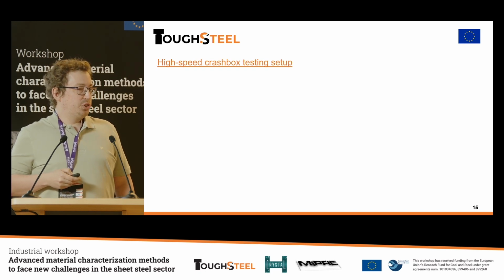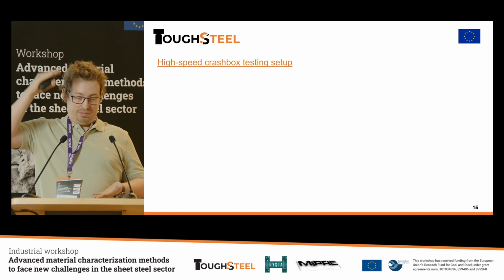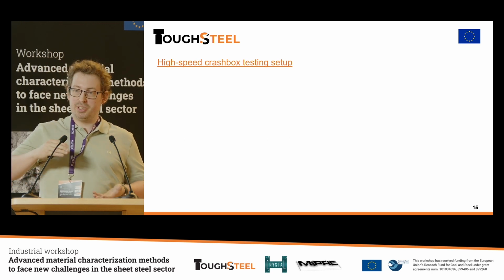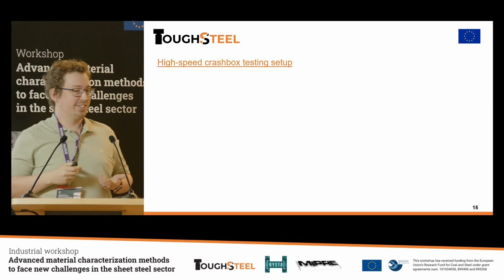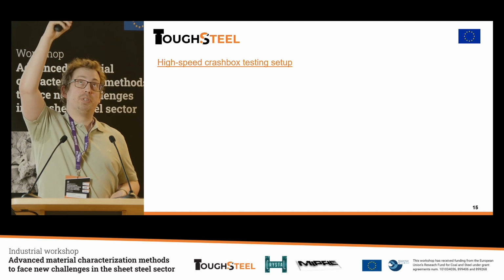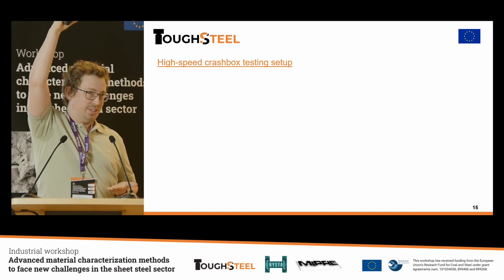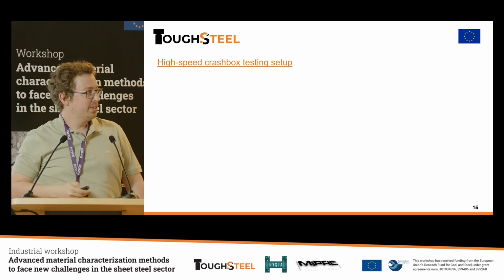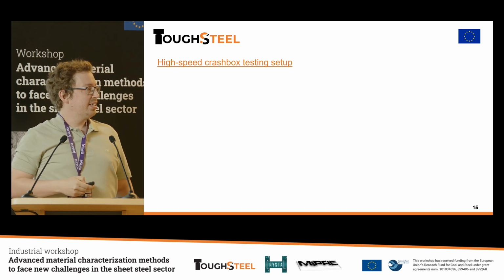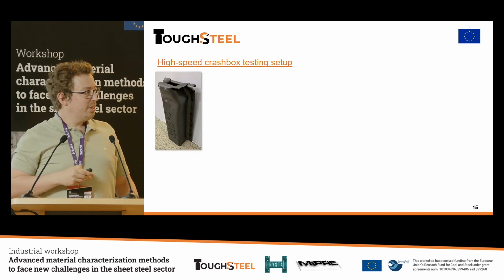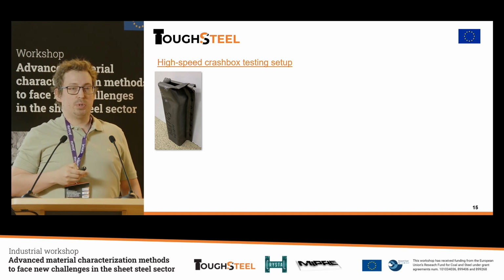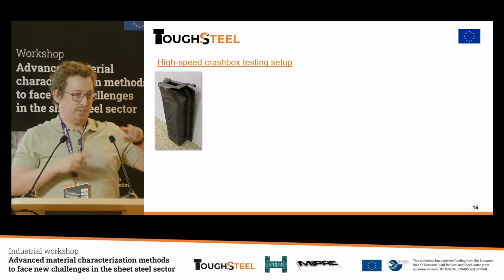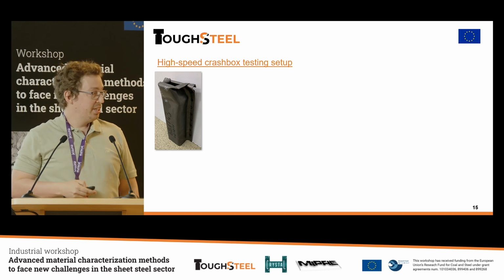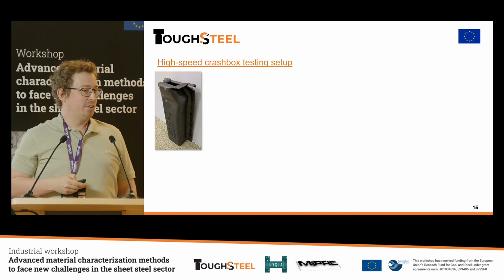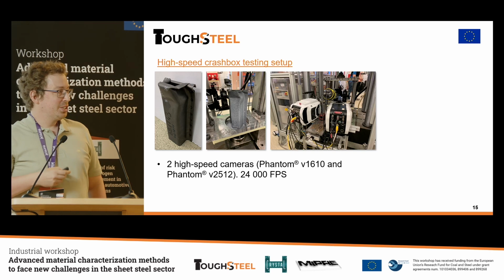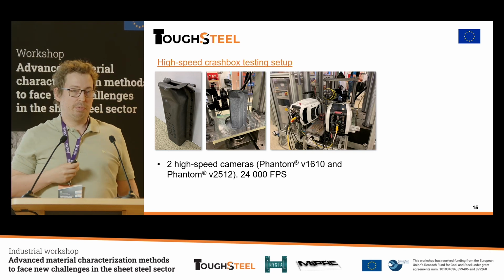And usually you use fall towers, like drop towers, to perform this with a huge weight. You drop it from a high level and crush the boxes like that. We don't have that. And usually you have maybe 5 to 10 crash boxes to get a good slope of the evolution of the crash index. We didn't have that either. We had 3 of every box. So we started to be a little bit creative.